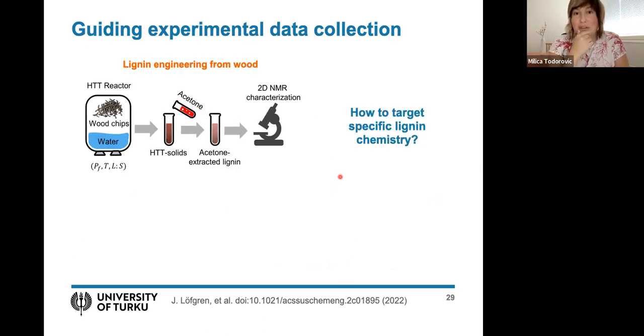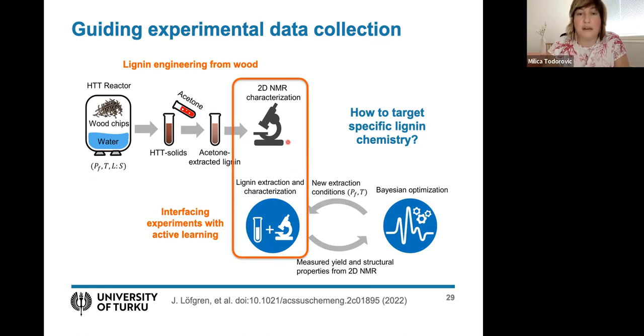But the real power of active learning is, of course, the data acquisition strategies. And this can be used to tell the experimentalist which experiments to perform to obtain their solution with as few experiments as possible. And this we applied to lignin engineering from wood. So the experiment was to put wood chips in water and heat it. This is called hydrothermal treatment. And then you extract some lignin with acetone, and you get your samples, and lignin is very difficult to characterize. So they put it in the NMR, and all they could see were different functional groups, so different for different lignin chemistries. And the question was how to adjust the processing conditions of this to target particular lignin chemistries, which are good for some applications. So what we did is we put the sample fabrication and characterization into a Bayesian optimization loop.